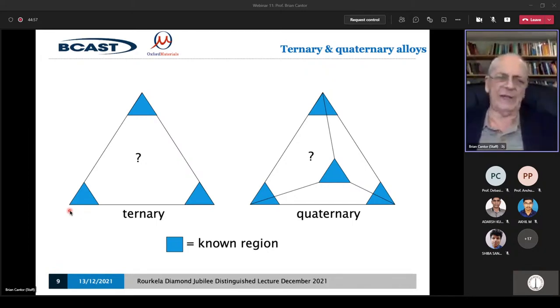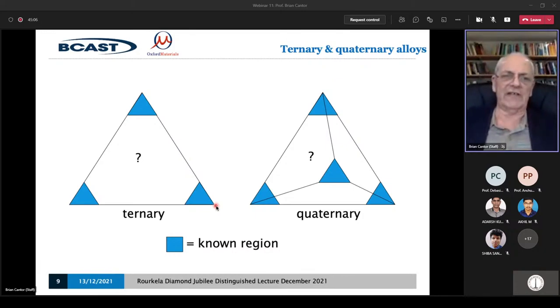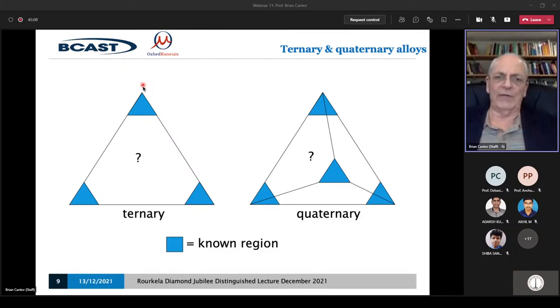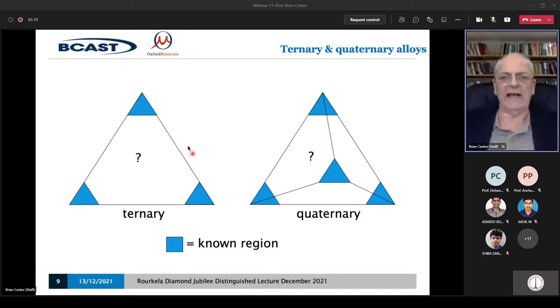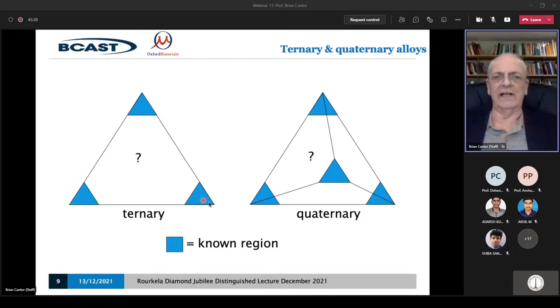So aero engines depend upon nickel superalloys. They're nickel, so we put nickel here, with a small amount of aluminium added, or sometimes titanium, but usually aluminium, to give strength. We'll put aluminium there, and a bit of chromium added to give corrosion resistance. So we have nickel with a few percent of aluminium, a few percent of chromium. We represent this on a ternary system, nickel, aluminium, chromium. And any point in this triangle is a different composition. The closer you are to here, the closer you are to pure nickel, here's pure aluminium, and so on.